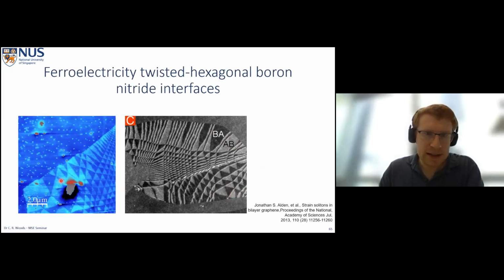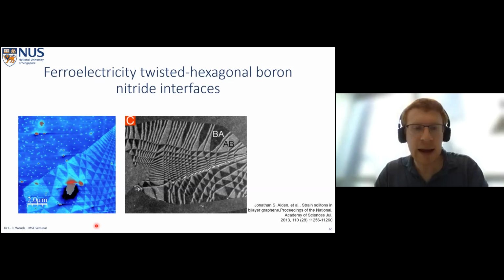And hopefully you can see that this compares really nicely with our work on twisted hexagonal boron nitride interfaces. So this suggests to us that our hexagons are probably for the parallel case, and we're seeing the difference between BA and AB.